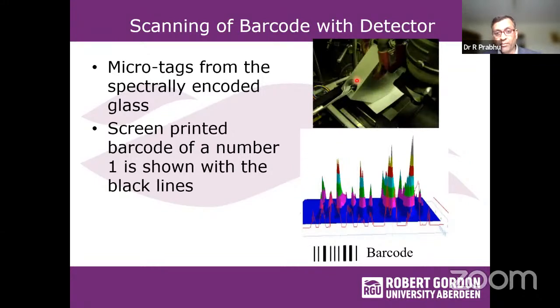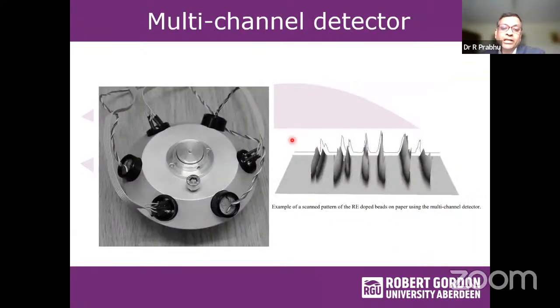Then moving from a single detector to a multi-channel detector, where we used all the three rare earth elements, we can still differentiate all the rare earth elements and have a nearly zero background level. The lifetime discrimination integrated into these detection systems improves the signal to noise ratio in this environment. So that's how we have done the spectral part of it.